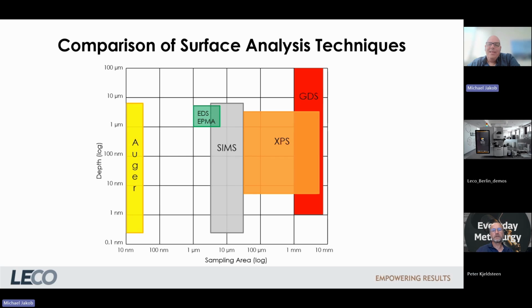And the big advantage compared to other surface analysis technologies like Auger or XPS or SIMS, and keep in mind this is a logarithmic scale, is that we can really go up to 100 microns and below. All others are anyhow limited to some 5 to 10 micrometers. And also the area, we're talking about production control or analysis, the area is of course 4 millimeter diameter in the standard equipment. We can also have a 2 millimeter anode, but let's stay at 4 millimeter. With others like Auger, you have a few nanometers surface you're really analyzing. So that's a big difference.